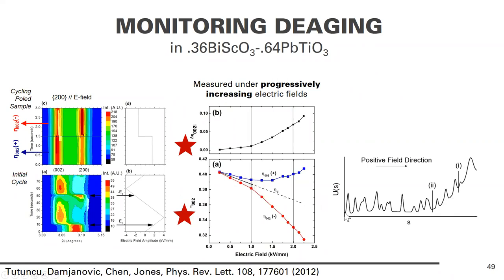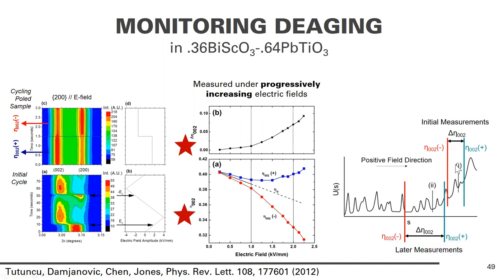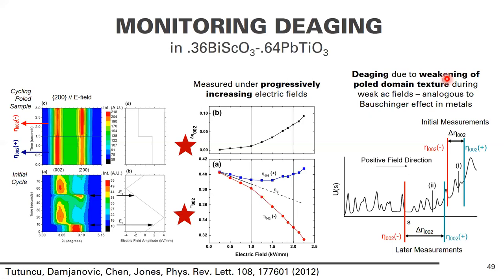We interpreted this in the paper in terms of an energy landscape. So you can imagine a domain wall going over energy barriers. And we suggested that the initial measurements occurred in a poled state where domain walls were pushed up against very large pinning centers. And so you could imagine cycling between this positive and this negative eta value, but then later, you've moved backward on average to a lower state on this energy curve, and that your later measurements, while larger in delta eta, are also on average a little bit less of a poled state. And so we found de-aging due to weakening of poled domain textures during weak AC fields.